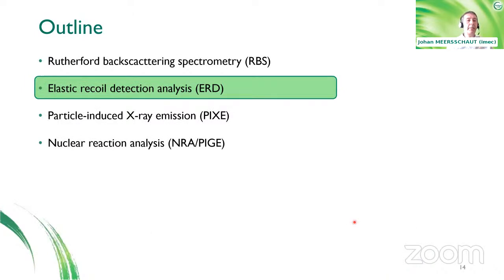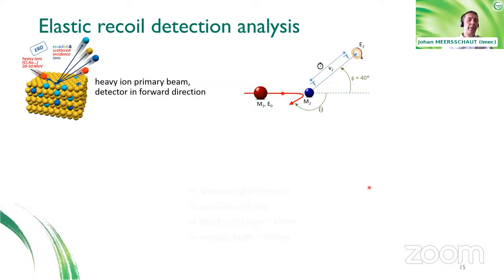And therefore, people in the past decades have developed elastic recoil detection analysis. So in this approach, instead of coming in with a light ion, you come in with a heavy ion. And instead of looking at the scattered particle, you will now look at the emitted, we call them the recoiled particles, out of the sample. Different from SIMS, you will not sputter the sample layer by layer, but you will, in a stochastic and statistical manner, eject samples from all depths in the sample. So you will statistically eject an atom from the top and from deeper inside the sample.